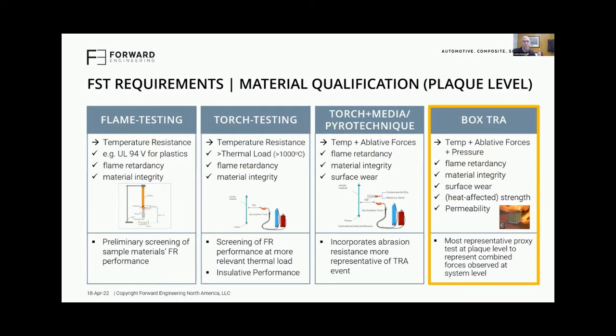And many of you may be familiar with flame testing, the traditional UL94 type testing, and that evolved into torch testing. So amping up the Q factor, the flow factor, how much energy you are putting into these samples, and measuring backside temperature, frontside temperature, and whether the sample withstands that. The reality is a thermal runaway in a battery enclosure is much more complex than just temperature. And folks had recognized that, and developed a torch and media or a pyrotechnic test. And there are different ways that you can include abrasive media or ablative forces on the samples when you're testing to screen materials for applicability in battery enclosures.